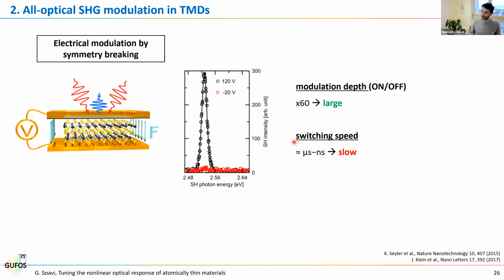Now, what has been done to date in order to achieve electrical and all-optical modulation? Electrical modulation in TMDs can be achieved in different ways. I always want to mention this paper, this Nano Letters from 2017, because this is the one that I like the most. Basically, what they do is they take a bilayer TMD with AB stacking. So when you take a bilayer and put them on top of each other, rotating them by 180 degrees, then the material becomes centrosymmetric, and there is no second harmonic anymore because there is no chi2 in the material anymore. So then they apply a vertical gate voltage, so an external gate voltage in the out-of-plane direction. By doing that, they break the inversion symmetry, and they can achieve a very large second harmonic.